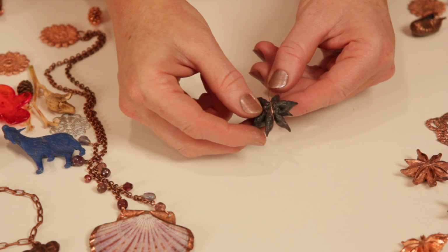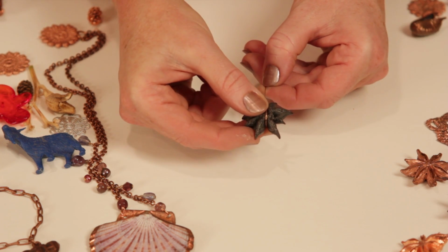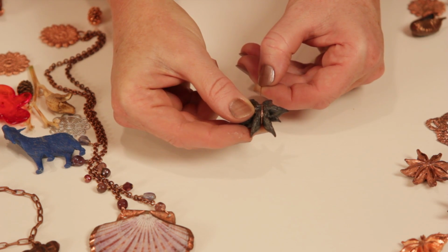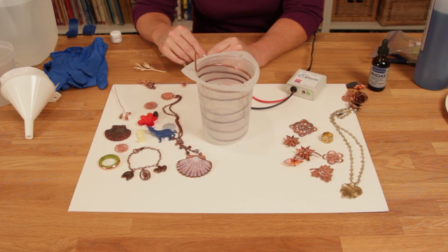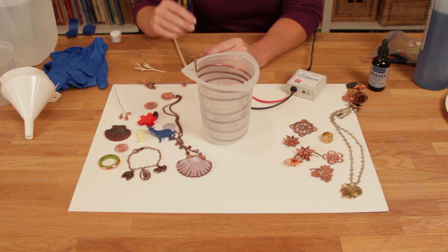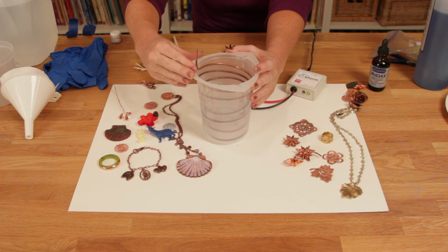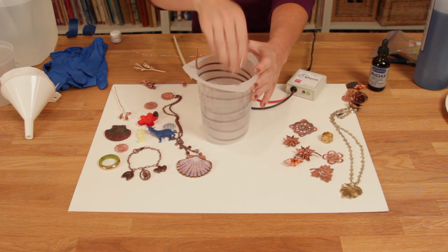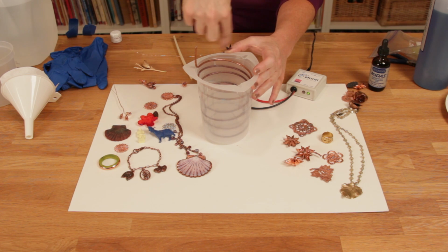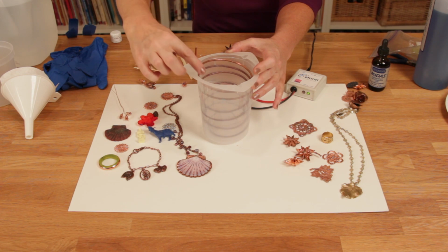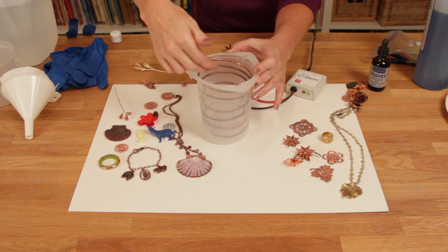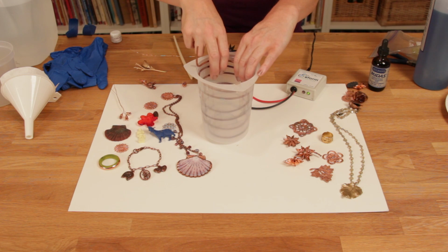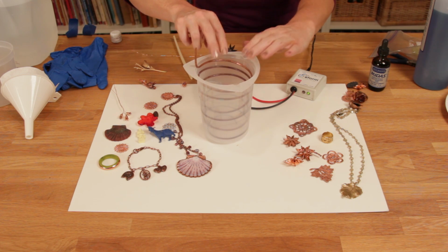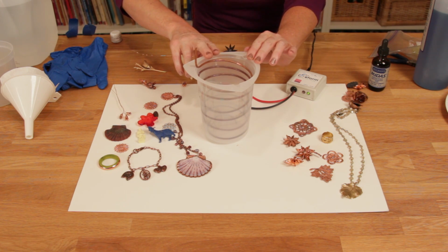After attaching the wire, I'm ready to go ahead and put it in the electroforming solution and attach the E3 Eform controller. After your piece is thoroughly sealed and coated with graphite, you're ready to electroform your project. Now, to start, I've got a beaker here, and I've got a copper coil that we've spiraled from the bottom of the beaker working up the side. That makes a nice anode that will transfer copper from all sides onto our object. You could just use a strip of copper, but we like this configuration because it fits nicely in the beaker. So we have that ready to go.